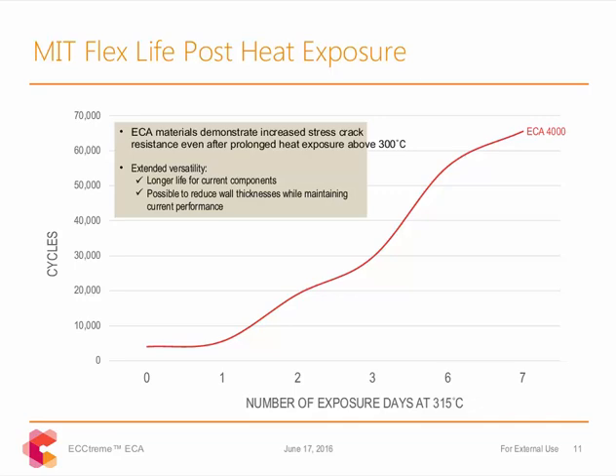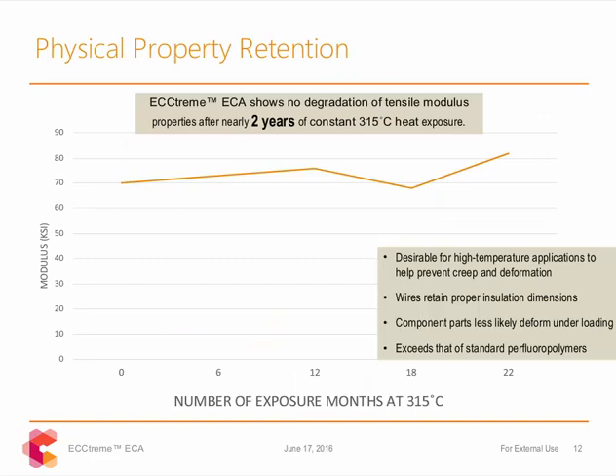One of the most interesting features of this material is that after almost 2 years of constant 315 degrees C heat exposure, there is virtually no change in tensile modulus. At the beginning of our development of this material, compression molded ECA plaques were placed in a 315 degree C air convection oven and sampled monthly for retention of physical properties. Though tensile and elongation measurements did gradually trend downward over time, the material shows limited drop in tensile strength and virtually no change in tensile modulus.